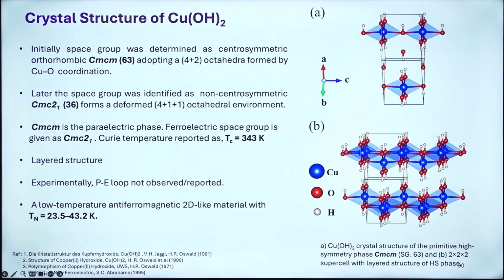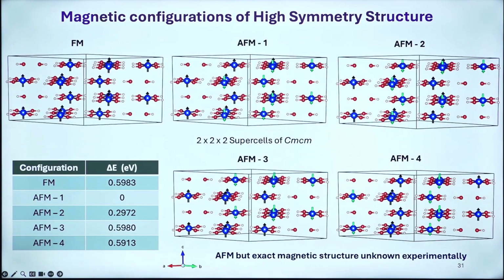That is the primary motivation for us to start this, and the magnetism is also there in this system. With all these things we started our calculation to see how best we could address this system. Since the system is magnetic, we made a 2x2x2 cell of the Cmcm structure and considered ferromagnetic and AFM 1, 2, 3, 4 configurations, because there is no precise neutron study available. It is hard work to compute, with around an 80-atom supercell. We could see that one antiferromagnetic alignment is more favorable in terms of the total energy.